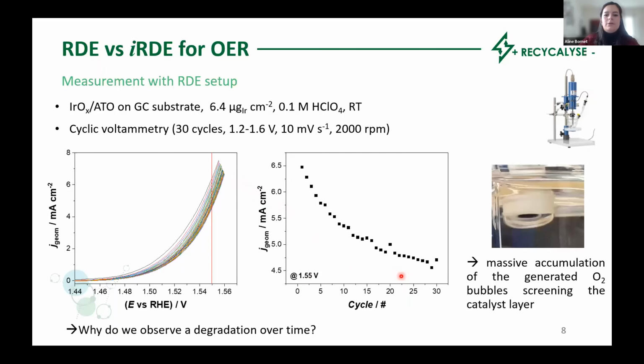In the literature, the decrease is often attributed to activity loss, but it is actually, as we saw before, due to a massive accumulation of oxygen bubbles on the catalyst surface. So we can clearly see this here on this picture.